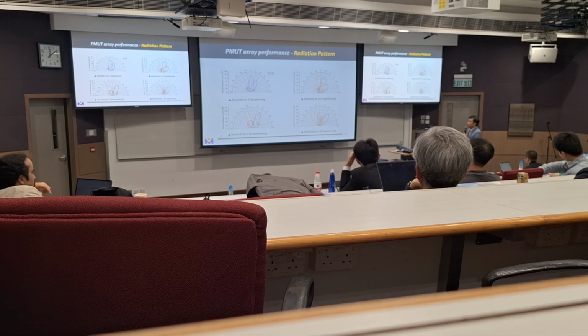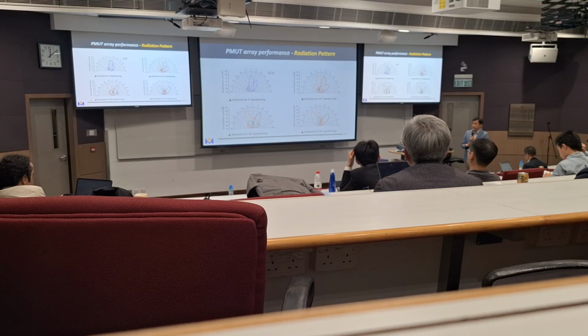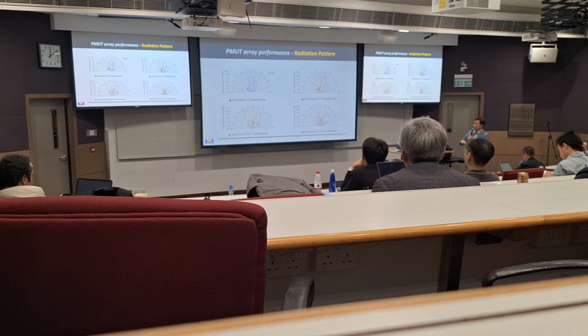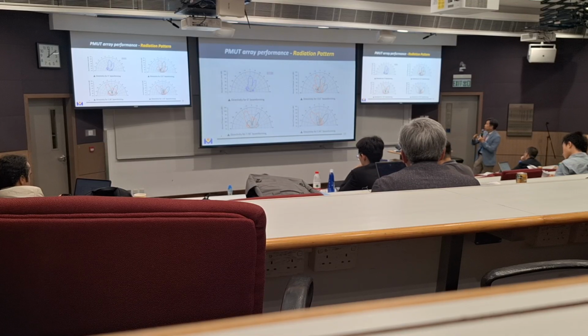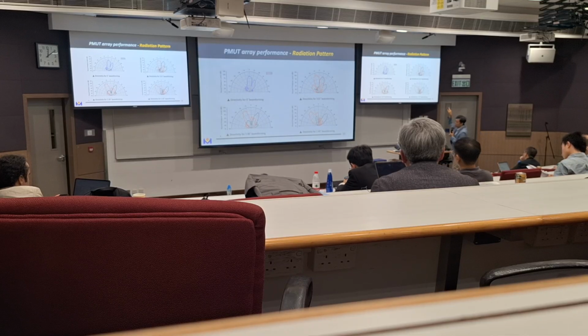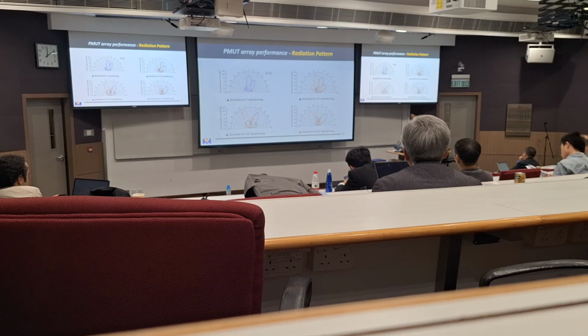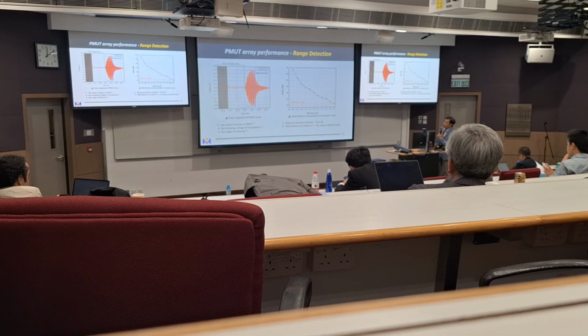Okay, and of course, not only the frequency response, we also need to do the beam pattern measurement of the individual array transducer, and also the beamforming array coupling angle test. From the right top view graph, we can see that if we control the beamforming to be minus 15 and positive 15, we can clearly see the main lobe is moving as we expected, and also at 30 degrees and 45 degrees. And this is the power signal we can get, and this is the PMUT ultrasonic transducer, so you can see the power signal is actually quite strong and quite clear.